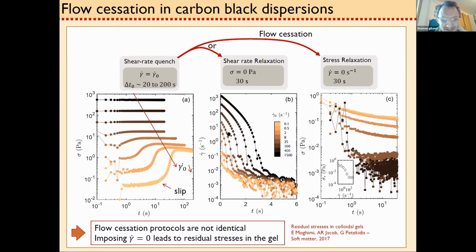And what you see is that this data is quite interesting, actually. You have first an exponential decay that tells you basically that you're stopping a fluid with some inertia, and then it drops down. You have those oscillations here. Those are creep ringings. So between here and here, basically, you've gone from a fluid state to a solid state. And this creep ringing and the going away from this exponential decay tells you that you're doing this sol-gel transition, basically. There is a lot, I think, to extract from those experiments. I haven't done any calculation on that, but I think there is much to understand here.